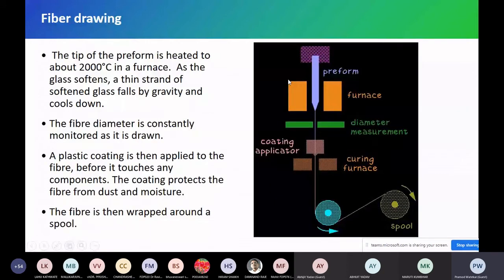So we take the preform here. This is a furnace, a graphite furnace. It can go up to 2000, 2300 degrees Celsius. So we put this glass preform here. Initially this glass is pushed slowly from top to bottom this way. So this tip gets heated and it melts. Once it melts, it comes down. We collect that drop, cut it, and pass it through the wheel that you can see there. We collect it on what we call a spool. It is rotating, so we slowly keep on heating and keep on pulling the fiber. This is how fiber is made.